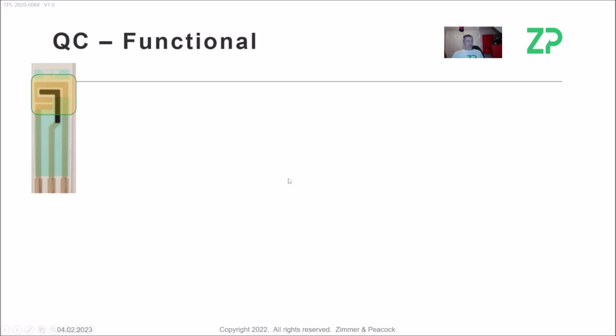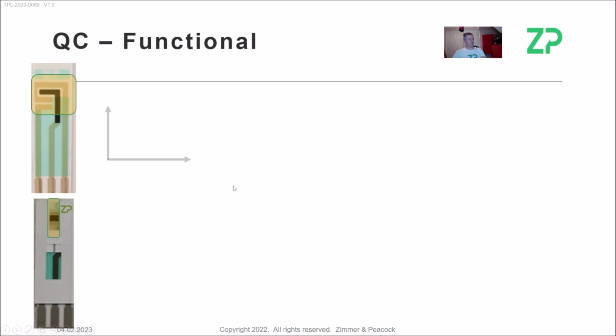So we have the electrode. It's been functionalized in some way towards the analyte of interest, and we could be doing that either before the microfluidics or after the microfluidics. You start to choose where to do this really based on the experience. What I mean by that is if your production line is generally yielding well, then you can wait to the end. But if you've got a problem in that deposition step of enzyme, maybe you have to go in and start sacrificing some sensors at that point. But the later you leave it in some ways, then the more representative of the final product that testing will be.